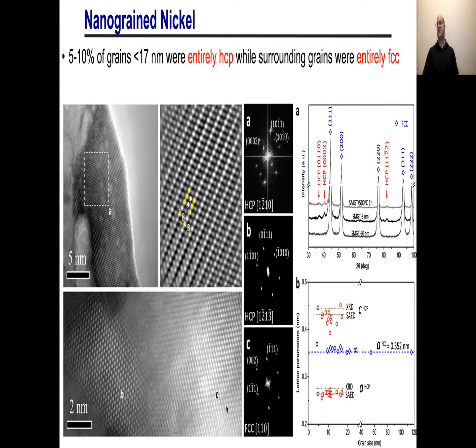Okay, and if you actually go in with X-rays and try to measure the lattice parameters from the spots, you'll find that if you look at different regions of different grain size, you always have things which are face-centered cubic with a lattice parameter around 3.5 angstroms. But you also start to pick out peaks associated with the A and C axis of the hexagonal close packed material. So the first thing I want to note here is that the transformation to the hexagonal material seems to be entire grains, not just along a single stacking fault or a small number of stacking faults in the material. It seems to be entire grains transformed.